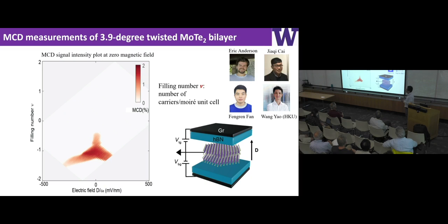Then we perform the same measurement on these. The data I show you is from 3.9 degree twisted MoTe2 bilayers. And here's a schematic of the samples. We have a dual-gated structure, meaning we can control doping in the sample. We can also control the perpendicular electric field across the sample.